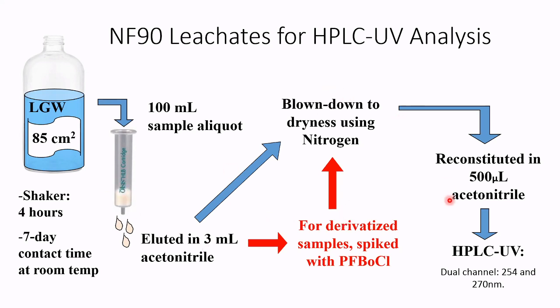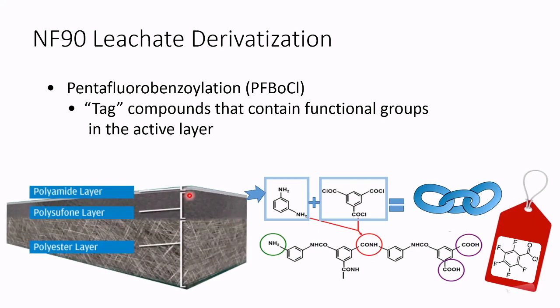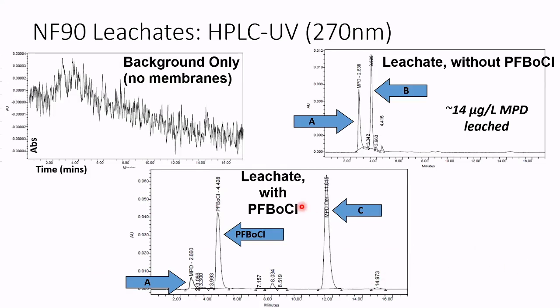So this in blue is our generalized approach for looking at membrane leachates. And here in red, we decided to derivatize a subset of those. We'll react with pentafluorobenzoyl chloride, which is our derivatizing agent, and then we can look for that as a tag. So if you look here, polyamide layer, the top layer of the membrane, we have those two monomers that reacted and created this fully aromatic structure. And now we're reacting it with pentafluorobenzoyl chloride to hopefully tag some of these functional groups. So if something is coming off, pentafluorobenzoyl chloride can react with amines and amides, for instance, and here's an amine. It can react with those functional groups, tag it, and then you have a way to search for these fluorinated groups if they're there.